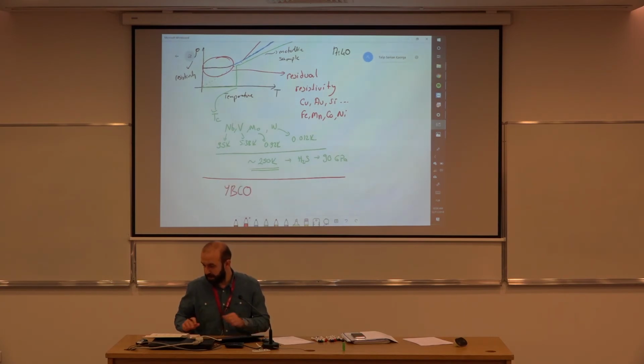YBCO. I need to be able to write down the exact formula. I need to cheat. It is yttrium, barium, copper oxide, and this is 6.9. And the transition temperature is 90 Kelvin, and that's already a very nice number because the temperature is above the temperature of liquid nitrogen. So at 77 Kelvin, liquid nitrogen starts boiling, and nitrogen is extremely abundant. It's very easy to liquefy.